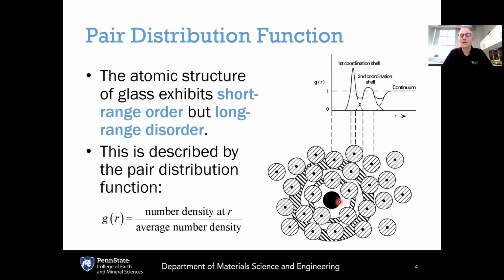Now, if you keep moving out from this first nearest neighbor shell, you'll see that this pair distribution function is dropping below 1 for some distance, and that's because you are less likely to find an atom here in this more of a void space between the first nearest neighbor and the second nearest neighbor. And that's because the first nearest neighbors have fairly well-defined positions. If you try to insert other atoms too close to them, those other atoms are going to be overlapping with the first nearest neighbors, which is energetically unfavorable. And as a result, this first peak is followed by a trough. This is lower than 1, and it doesn't rise above 1 again until you get to the second nearest neighbor. So the second coordination shell is given by the outer circle shown here.